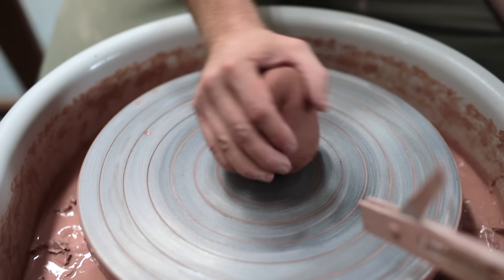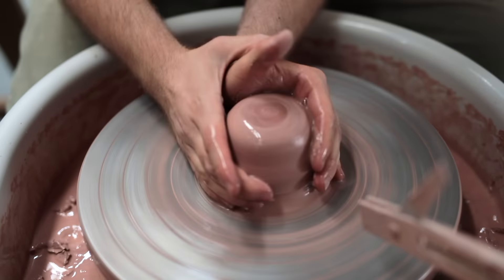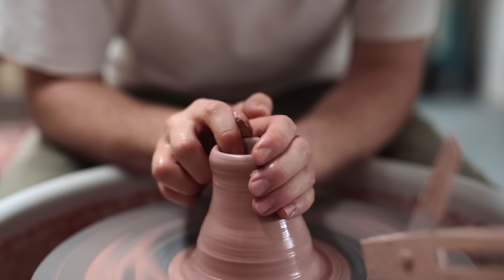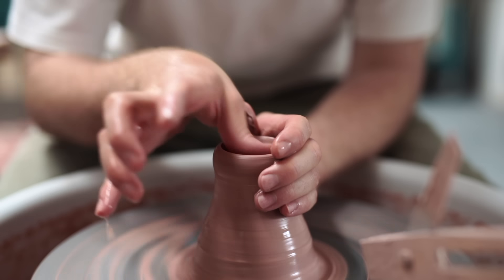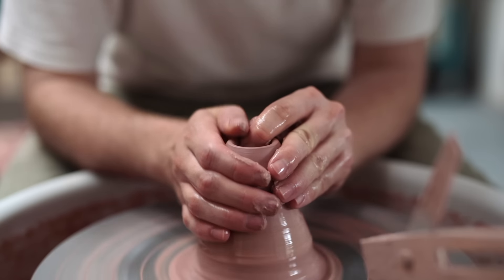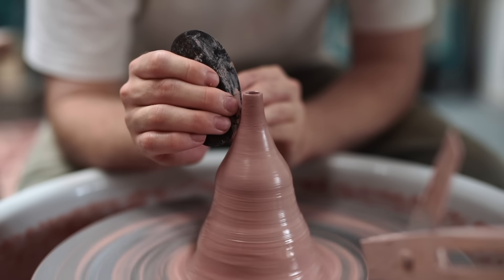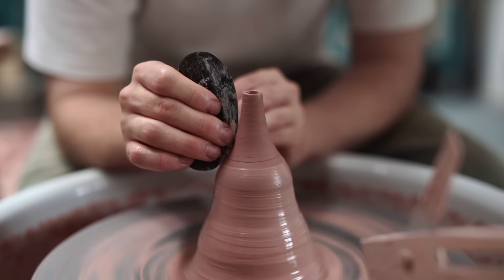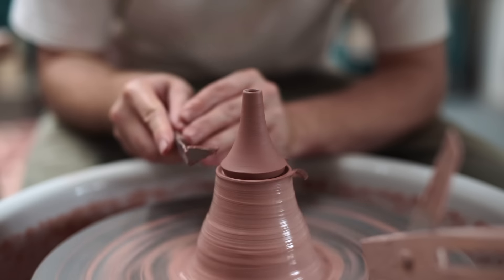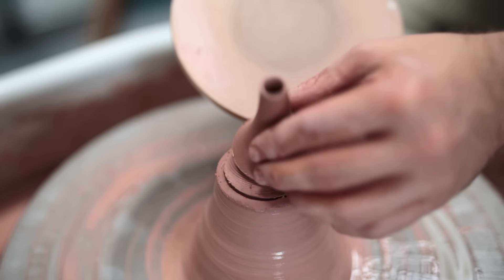All that's left to be thrown is the spout. I'm using a much larger piece of clay for this, but I'm not just throwing one large spout — when I make spouts, I like to throw them off the hump. This is the process of throwing a smaller pot atop a much larger mass of clay, and for things like spouts that can be a bit finicky, I prefer this method. I'm also going to make about two or three spouts, as they're still probably the thing I'm most unsure about when creating teapots, so I'd rather give myself some options. I initially throw my spouts with relatively thick walls, then scrape over them from the outside, thinning them and creating the profile I want. I do a second pass to smooth them, then trim away a groove around the base to define an area I'll drag the wire through.